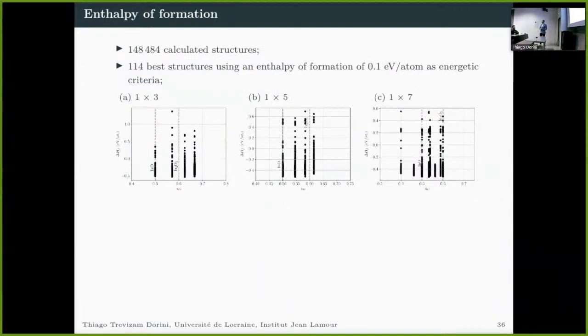So here we have the results for the formation energy. All the phases that we have calculated using the USPEX code. So you can see that there's more than 100,000 structures. And as you can see on the graph, these 3 formation energy graphs are the 1x3 results, 1x5 and 1x7. And based on an energetic criteria of 0.1 electron volt per atom, we have selected 114 best structures to study